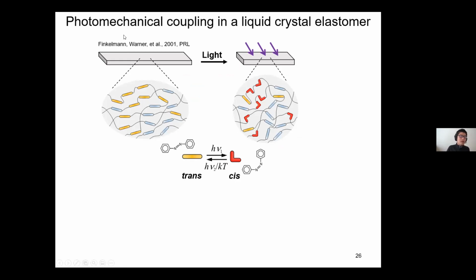So this was an experimental observation first discovered by Finkelmann and others. So what they had is a liquid crystal polymer network. So these are liquid crystal mesogens, and you mix some azobenzene in it, and you shine a light. This material can contract with very large deformation, like tens of percent strain. So the mechanism is that with the photoreaction, this kinked shape of cis will disturb or mess up the long range directional order of these liquid crystals. So they shrink, okay?